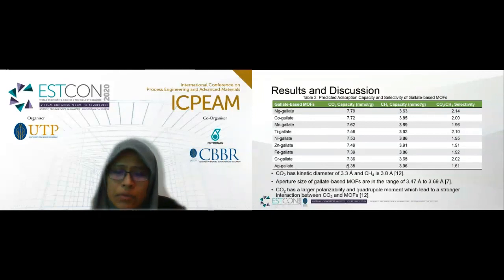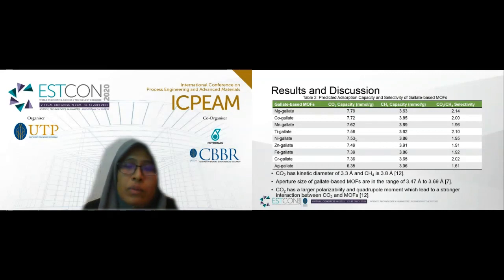Since the capacity of CO2 is higher than CH4, all the selectivity values are more than unity. The adsorptive selectivity occurs due to the difference in affinity of components in the gas mixture to be attached on the porous surface of MOF. Selectivity can be simply understood as the affinity of gallate-based MOFs to adsorb CO2 compared to CH4. Therefore, it can be concluded that gallate-based MOFs is prone to selectively capture CO2 compared to CH4.